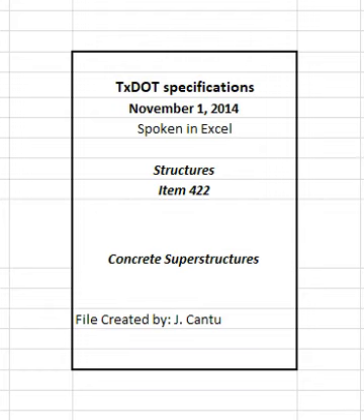Make at least one set of test specimens for each element cast each day. Cure these specimens under the same conditions as the portion of the structure involved for all stages of construction. Ensure safe handling, curing, and storage of all test specimens. Provide testing personnel and sample and test the hardened concrete in accordance with Section 421.4.8, Sampling and Testing of Concrete.